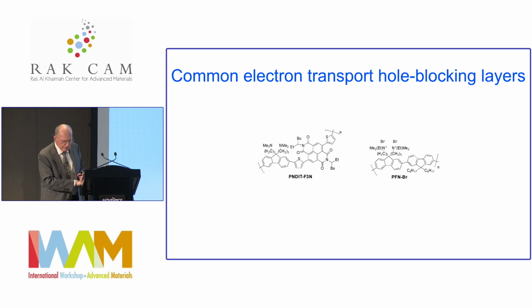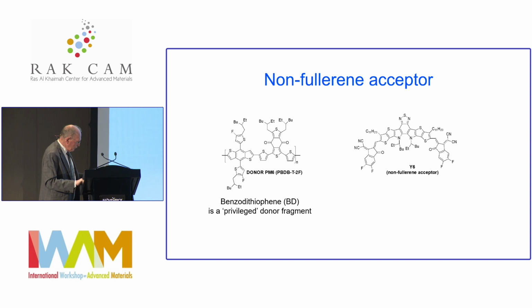So I need to introduce a few structures which will appear with acronyms under them. And if you've got any memory, I'm struggling to remember them myself. But electron transport hole blocking layers to facilitate the negative charge going in the right direction have emerged. A copolymer here in which there are amino groups and some electron accepting groups over here, and a copolymer in which these are alkyl ammonium groups with halide counterions. And they've been used quite a lot. That's just to filter the charge direction. And then a non-fullerene acceptor that's emerged is this one here on the right, and you'll see that referred to as Y6 or some derivative with Y in charge in front of it.